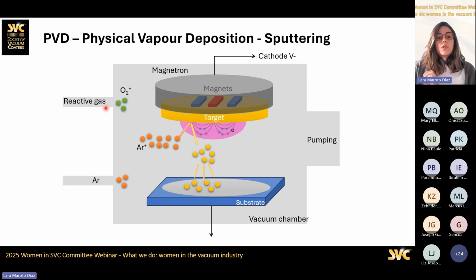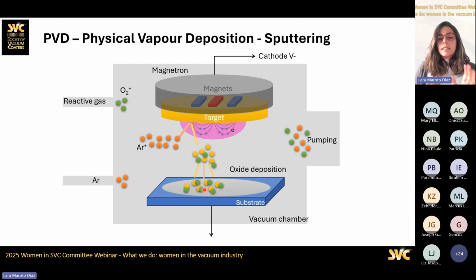And when you introduce a reactive gas, in this case I have put oxygen, but it could be other kinds of gases like nitrogen, this gas is going to react with the material that is coming from the target, and that is going to form a different type of layer, which in this case could be an oxide deposition. And then after that, all these gases are continuously pumped down, so you maintain the level and the cleanness of the vacuum. And this is more or less overall how sputtering works.